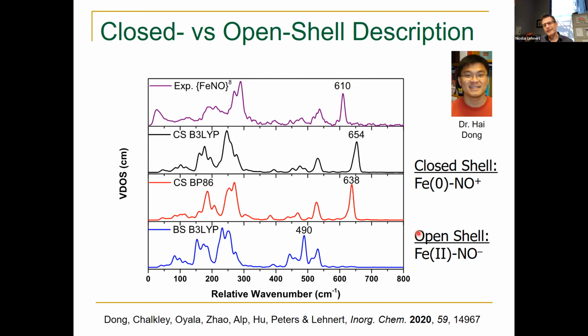But if you go to an open shell system, so something like iron 2 NO-, and you perform DFT calculations on this, you can see that especially the iron NO stretch is completely off, right? And so that was really remarkable, because if you look at the geometric structures that you get from the DFT optimization, there was almost no difference between the closed shell and the open shell structure. But the vibrational profile is very characteristic, and we can assign the electronic structure for the series as being best described with the closed shell model. So that gets the smiley.